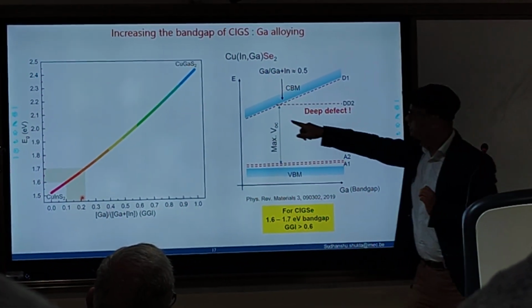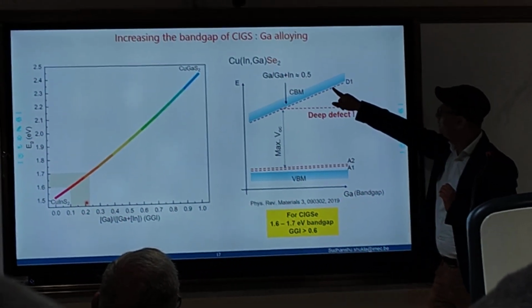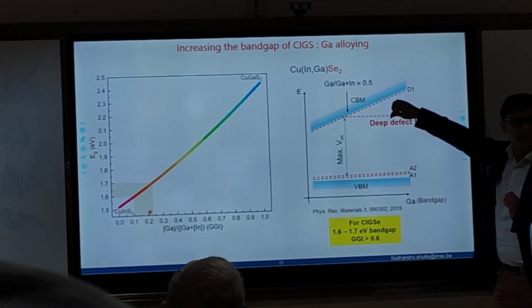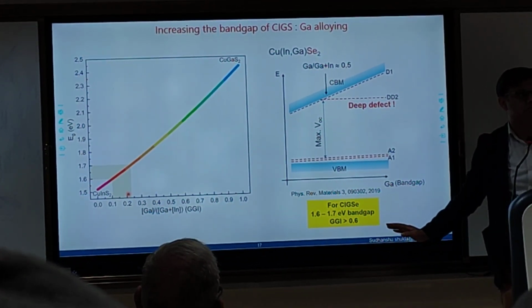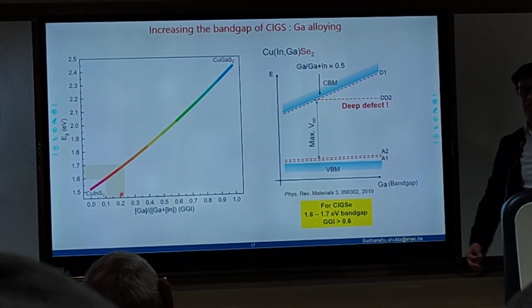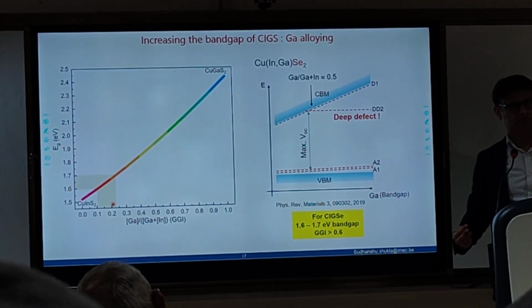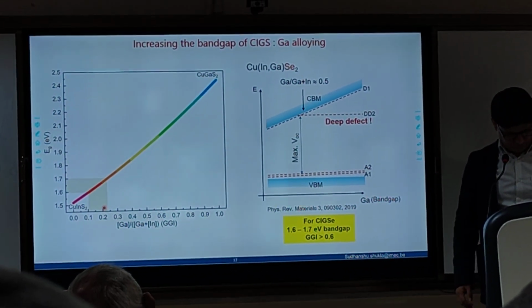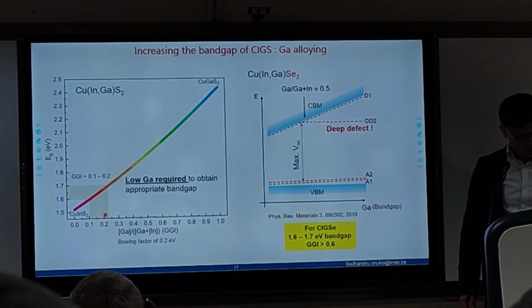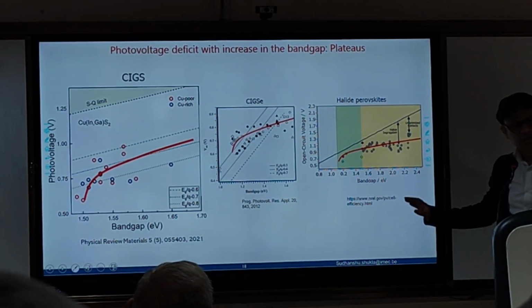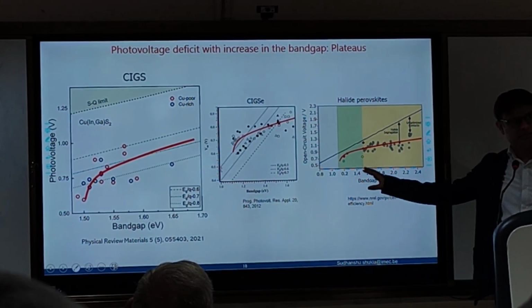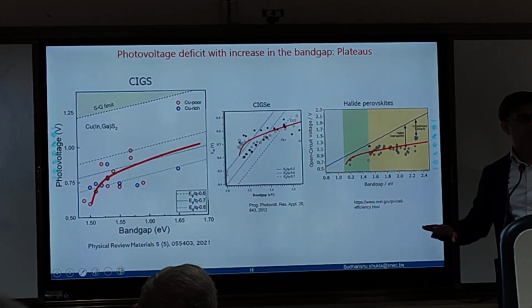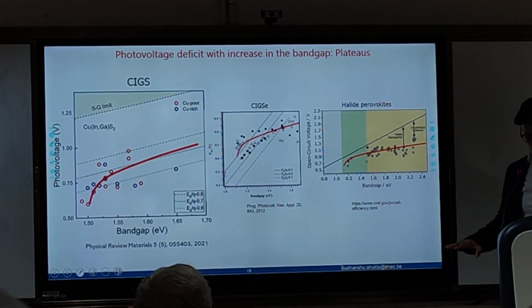So what happens? Here everything is fine, but as soon as you are here, the carriers just relax to this deep defect and these carriers are lost. So the same defect becomes detrimental when you increase the band gap. Okay? Now, skip that. This is a very profound and fundamental problem. In fact, this can become a good proposal in itself. And let me show you how.